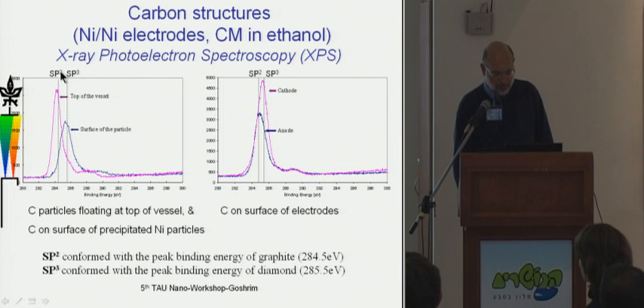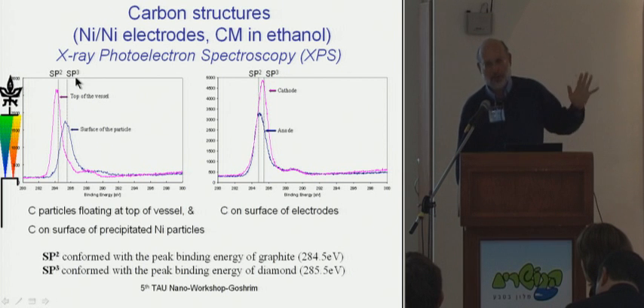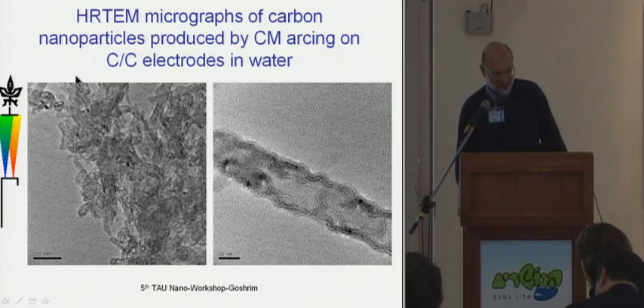On the other hand, particles that were collected on the surface of nickel particles, as well as particles that were collected electrostatically, in a process which I'll describe in a minute, on an electrostatic collector placed in the liquid, had a binding energy which is much closer to sp3, which is diamond-like binding. Now, what this means, I'm not quite sure, but for what it's worth.